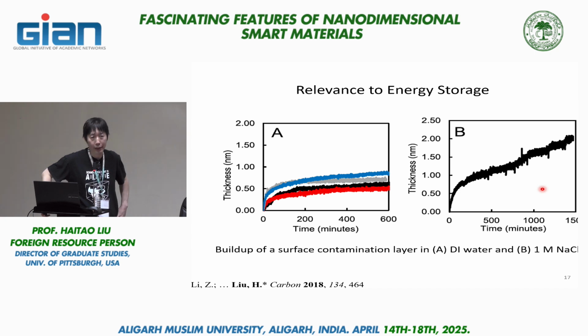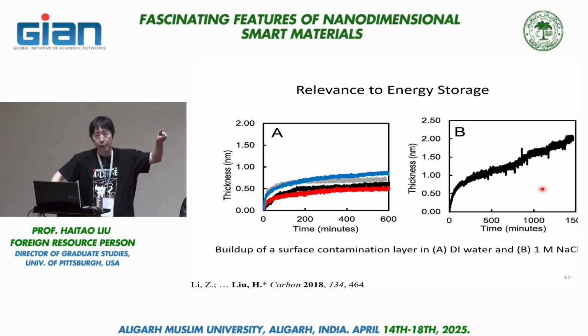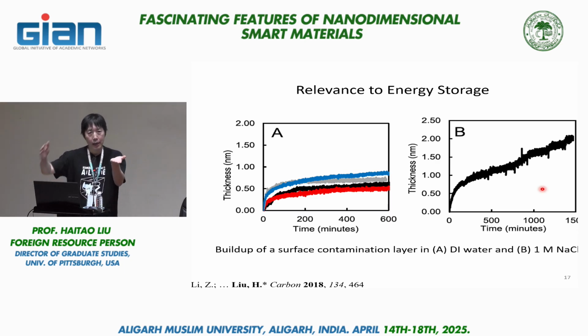Okay. Now to move one step further, I want to talk about contamination, not in air, but in aqueous solution. So what I show here are ellipsometry measurements. You may remember I showed some of this in an earlier episode where we look at ellipsometry measurement of graphite exposed to air. Now here I'm doing the same kind of measurement, except I'm doing everything in water. Okay, so what the experiment is, I have graphite. I expose the graphite to some aqueous solution. And then I have a laser coming in, shooting at the liquid-solid interface.